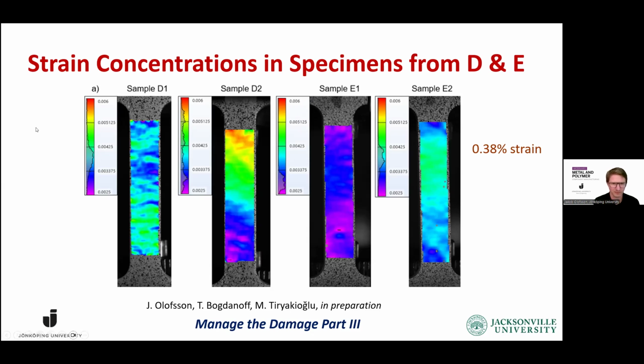And interesting is that the 2 samples to the left, which we now suspect to contain a much higher level of oxide, show a much more dispersed strain field. You can see that there are small histograms included in the scale bars, and especially for sample D2, you can see that the strain distribution is very dispersed. There's big variability of the strain because we have this large amount of hidden damage, which is causing a lot of strain concentration. So there's a competition between all of these internal damages. In the samples to the right, E1 and E2, we can see that the histograms are much more narrow at a certain level of strain. And here the level of hidden damage is lower.